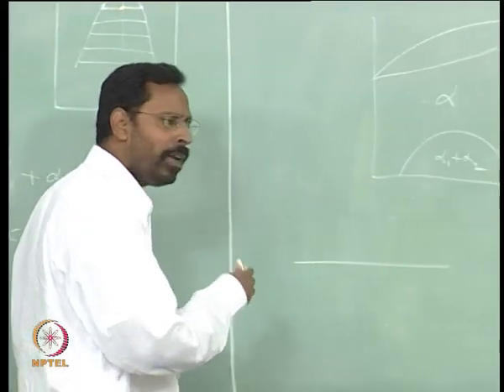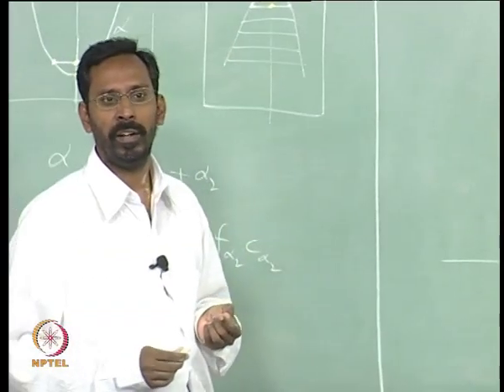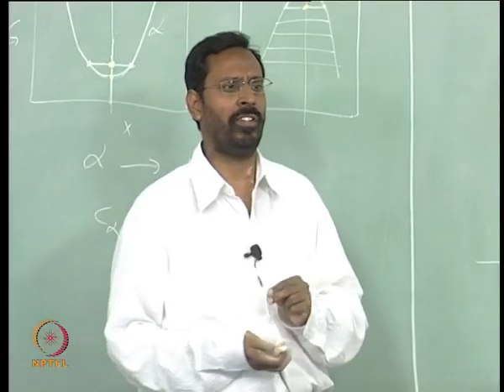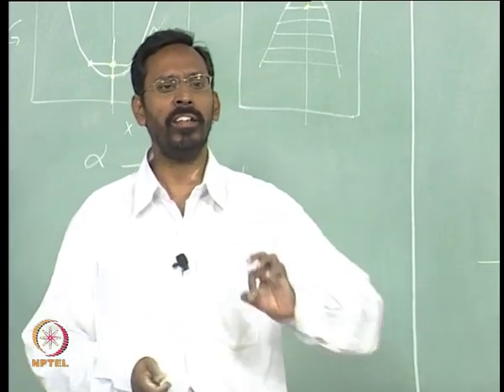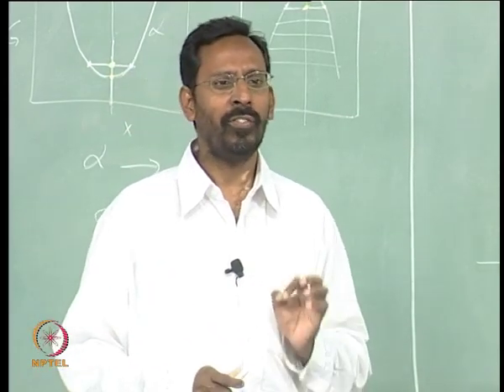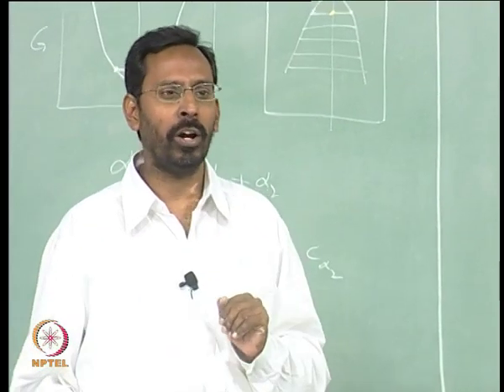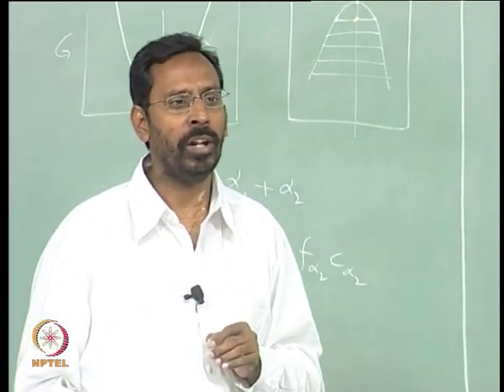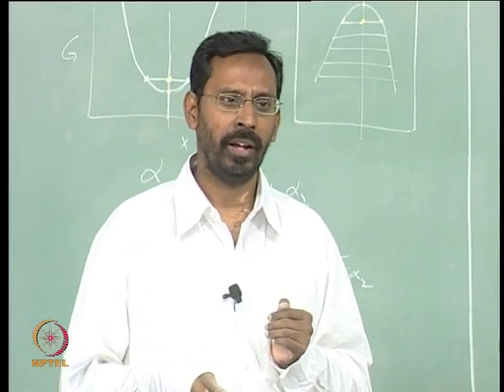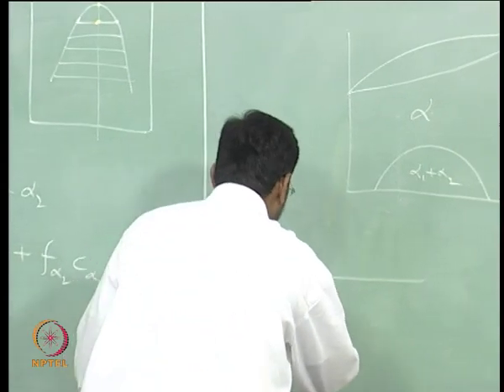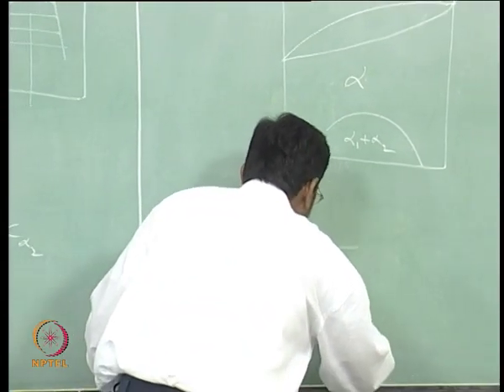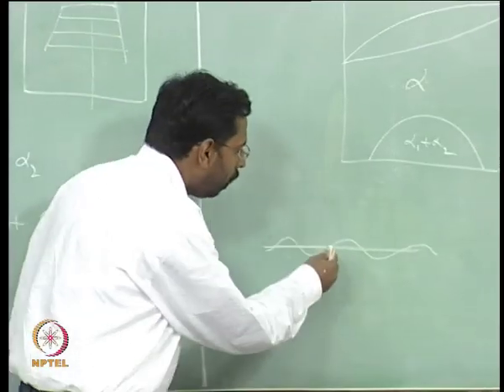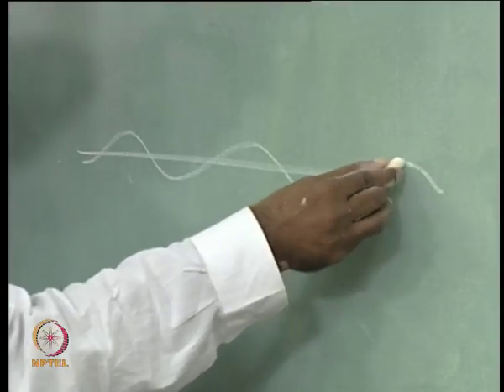So what happens is there will be a small fluctuation, even a small thermal fluctuation. Whenever you say this alloy is at 500 degrees centigrade, that is a bulk temperature that you are talking about. In a small nano region, you can always have small changes, and this can cause compositional fluctuations in such a way that there is a small region where the composition decreases and another region where the composition increases. Though I have drawn it with such a scale, this can happen at less than a nanometer scale.